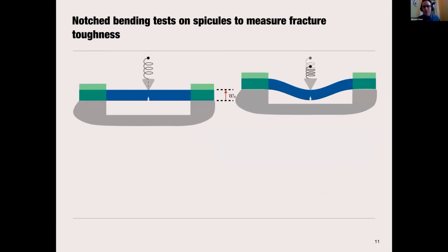When we perform our bending test, we move the stage up and we measure the displacement of the stage, W sub S. In the process, the cantilever deflects an amount W sub C, and we measure the force based on the cantilever's stiffness and its deflection. And we can compute the deflection of the load line, or the displacement of the cross-section of the spicule, W naught, based on those measurements W S and W C.